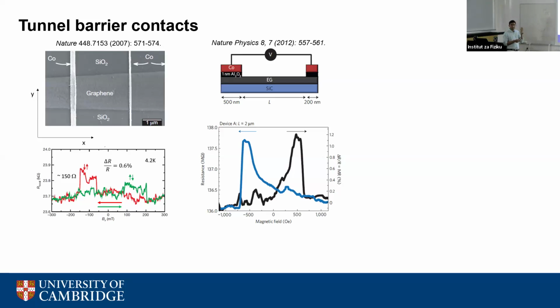But if you insert a dielectric which is 1 nanometer thick, you can see the device resistance increases to hundreds of mega ohms. Graphene should be quite metallic. It should be in kilo ohms resistance. But introducing this layer makes it hundreds of mega ohms. If you make a device which is hundreds of mega ohms, it will really slow down your entire circuit. It's not really useful. So we need to make devices that will be efficient in spin injection and also low resistance.